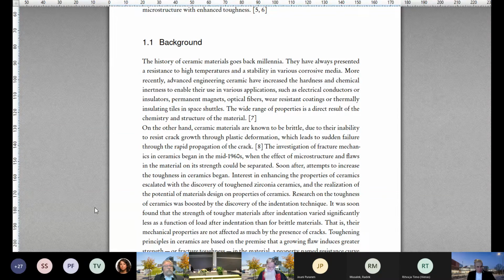And later during the thesis, I did discover that they are actually beneficial for strain tolerance in the sense that they're pre-existing cracks. So to make a new crack, you would first open the old ones, so that would give a bit of leeway to strain. And this, for example, in thermal cycling applications would be beneficial. There's no additional cracks coming, it's just old ones opening and closing.